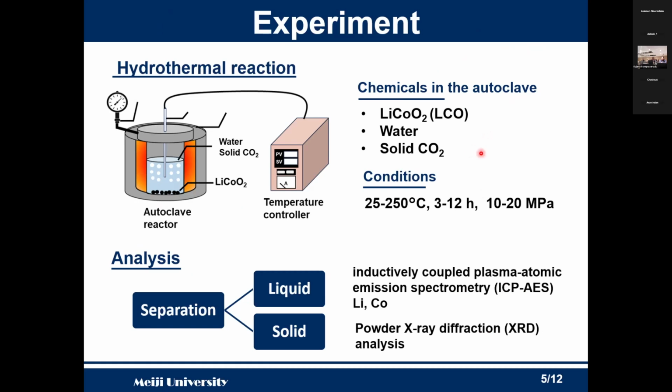The conditions are temperature, reaction time, and pressure. After the hydrothermal process, the mixture is separated into liquid and solid. Lithium and cobalt in the liquid are analyzed by ICP-AES, and the solid is analyzed by powder XRD.